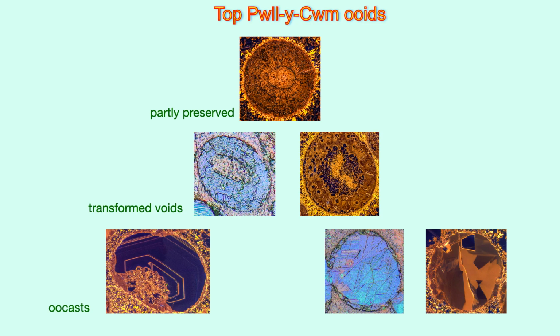In contrast, dissolution of ooid cortices resulting in oomolds was complete. Any ooid nuclei left after dissolution were unsupported and came to rest against the intergranular cement. The filling of these oomolds occurred during periods of alternating precipitation and dissolution.